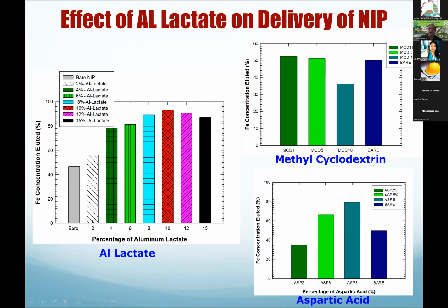And then methyl cyclodextrin showed slightly reduced positive charge, that shows this. And then aspartic acid, basically based on the zeta potential measurements, these three have the options. And then with the different percentages, you can see up to 80% of the nanoiron particles that are introduced from the top could be collected at the bottom. The 20% is retained or trapped in the sand. That's fine, because at the end of the reactions, that becomes iron oxides, and similar to other oxides you have in the soil, they remain trapped in the soil.